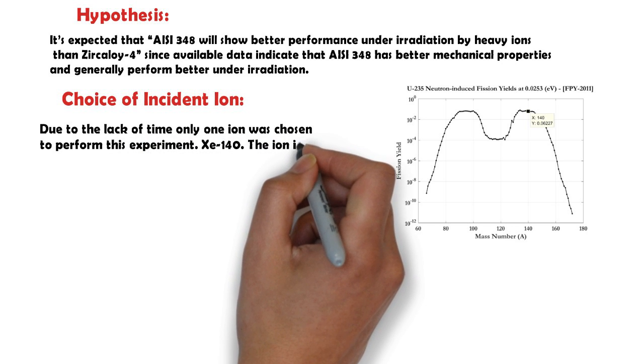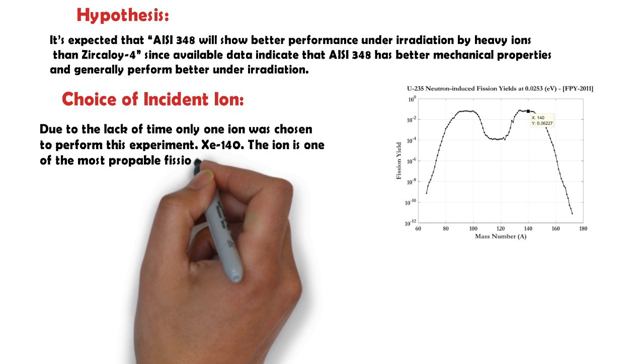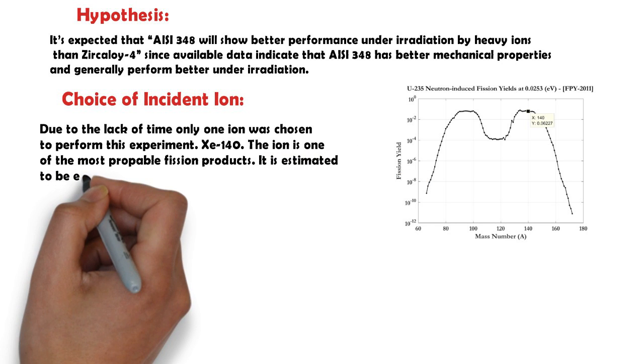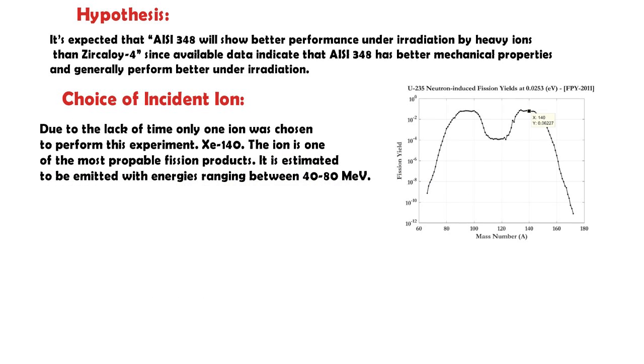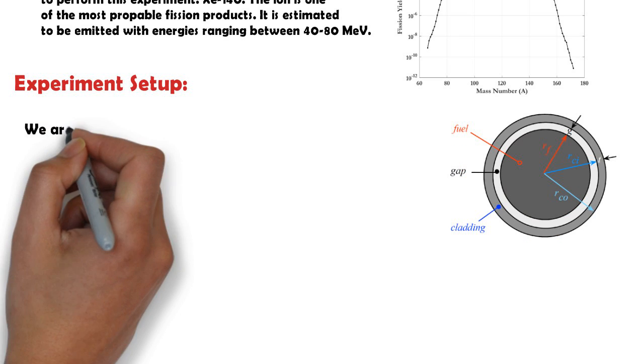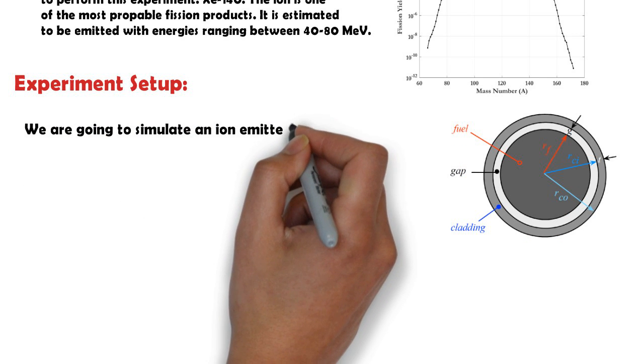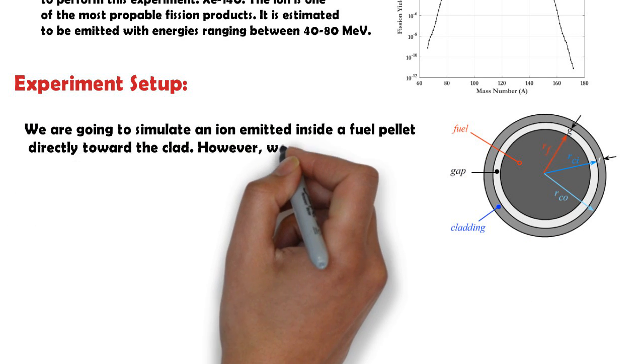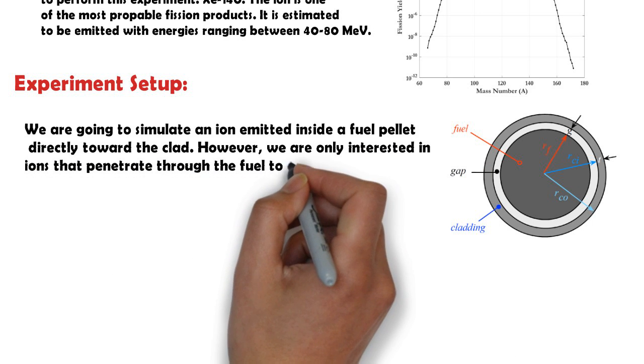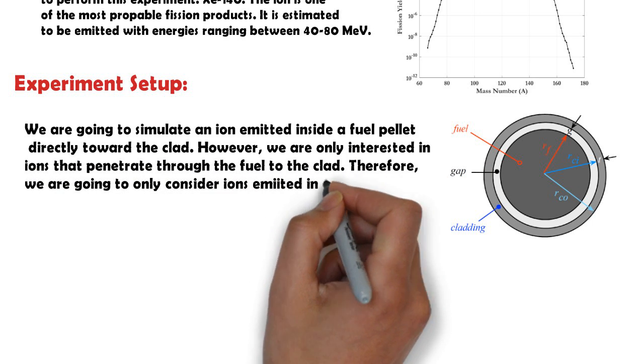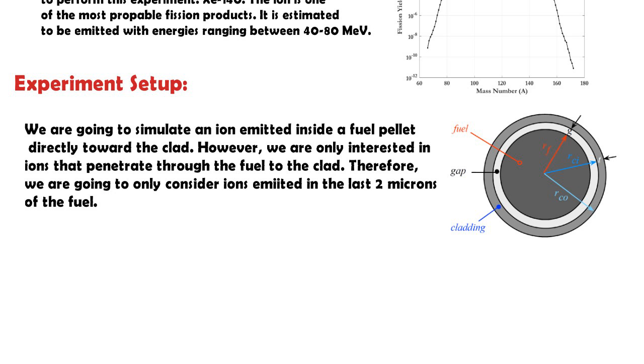The ion is one of the most probable fission products. It is estimated to be emitted with energies ranging between 40 and 80 MeV. We are going to simulate an ion emitted inside a fuel pellet, directly towards the clad. However, we are only interested in ions that penetrate through the fuel to the clad. Therefore, we are going to only consider ions emitted in the last 2 microns of the fuel.